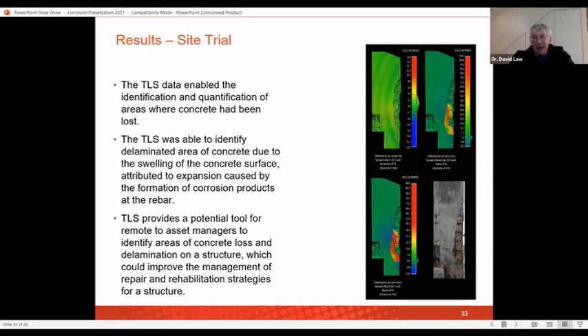And we had not expected to see that at all when we'd done this scan. We were just thinking we might be able to see cracks appearing. But what we could see is when we started at the beginning of the 2-year period, that was the position. And then after about 9 months, we got to here. And then after about 18 months, 2 years, we got to here. And then about another year or so later, this bit of concrete actually fell off.